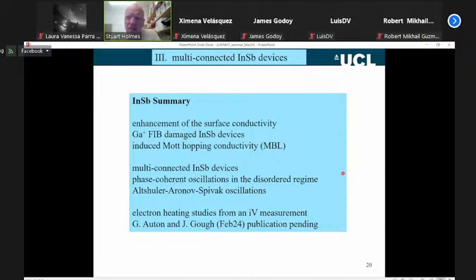What we also haven't done is get the thermal isolation yet. We want to develop the thermal isolation in this material system. We can induce this hopping conductivity effect, which is essential for looking at localization effects. We've got these multi-connected devices now, these kind of anti-dot systems, and we've started to see these phase coherent oscillations in this disordered regime. So the electron hops around the structure, but it still retains the phase. We can still pick out the phase, even though it's in the hopping regime. That's this so-called Altshuler-Aronov-Spivak oscillations.